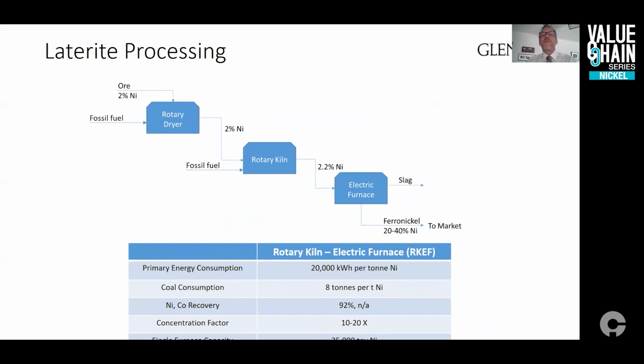The process used for smelting nickel laterite ore bears some similarities to the electric furnace process for sulfides. Due to the absence of sulfur in the ore, fossil fuel is required for drying and preheating the ore. In the rotary kiln, approximately half of the nickel is reduced from oxide to metal using carbon. In the electric furnace, the remaining nickel and a portion of the iron are reduced to metal. Control of the extent of iron reduction determines the nickel grade of the product.